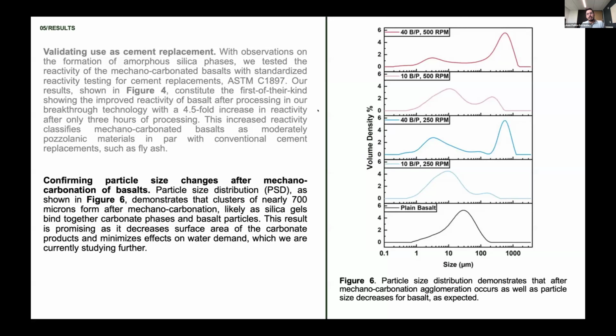Another key consideration here that I meant to highlight in previous results is that milling energy, how fast we're spinning our rotor in that reactor, signified by the revolutions per minute here, 500 or 250 RPM, really shows that there is no real difference in either the reactivity or the carbonation.